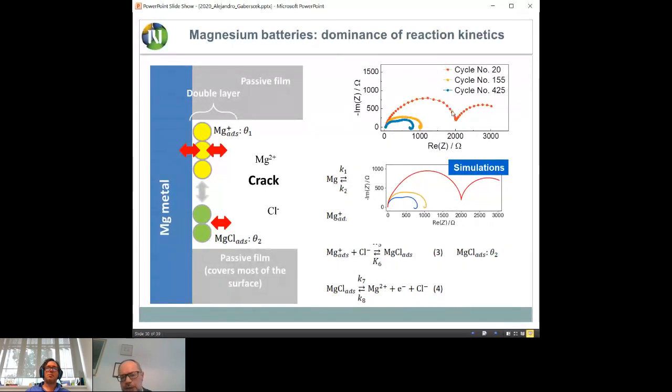It's interesting that from here to here, so these are different cycles of magnesium. Magnesium is symmetric. You see some drastic changes in shape, but if you analyze this, you will see that this just means that there is a little bit more and more of this, and a little bit less and less of this as a cycle. There are no other essential changes, and you already get this spectra, which fit quite well to the measurements.